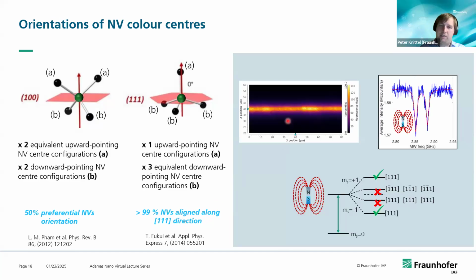And this is visible here. So this is a 1-1-1 diamond layer, and this is the ODMR signal where you only get these 2 dips originating from these ms plus and ms minus 1 states that are related to the 1-1-1 direction that is along the surface normal of the 1-1-1 diamond.